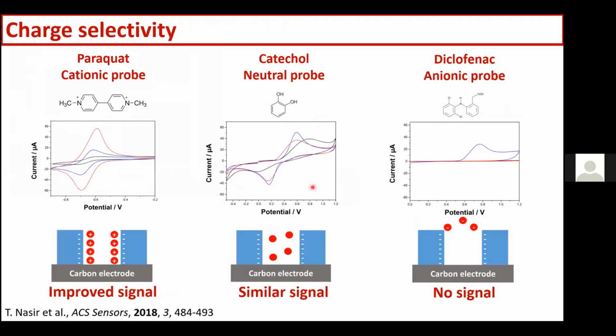And so the first thing that we tried to do when we wanted to use those for sensors is to look at the charge selectivity, because at pH 6 the silica is negatively charged. So we looked at a cationic probe, paraquat, a neutral probe, catechol, and an anionic probe, diclofenac. And here on all these cyclic voltammograms, the blue line is the bare electrode, the red is the modified electrode, and the black is the blocked electrode